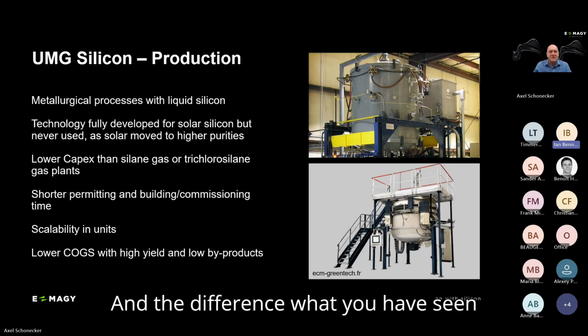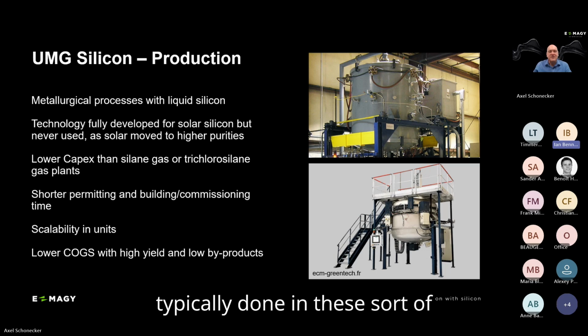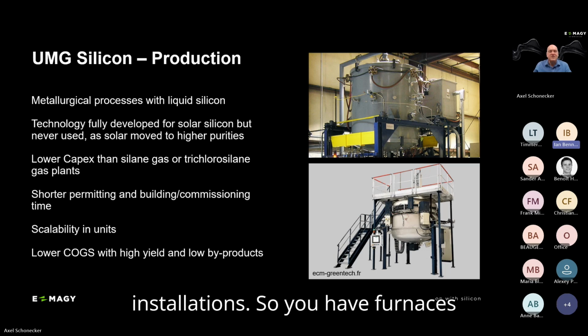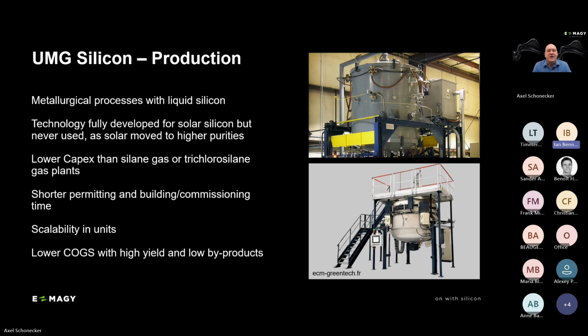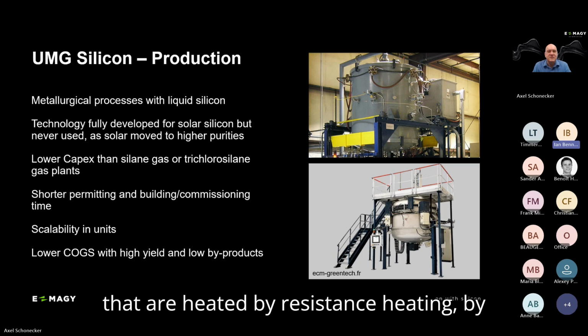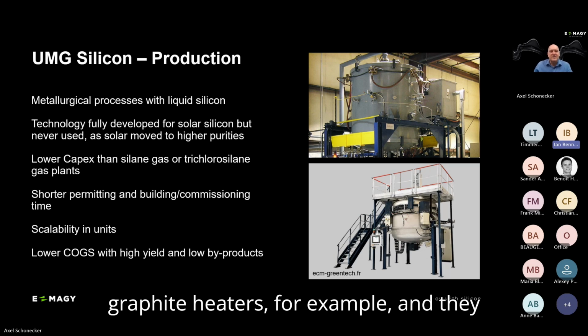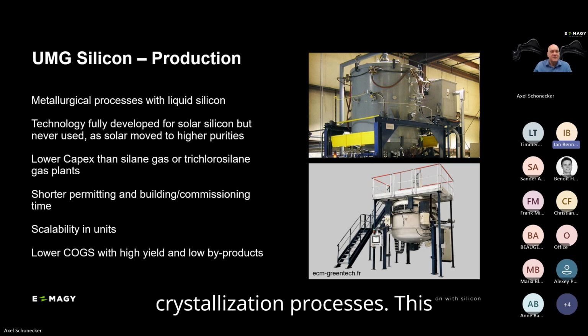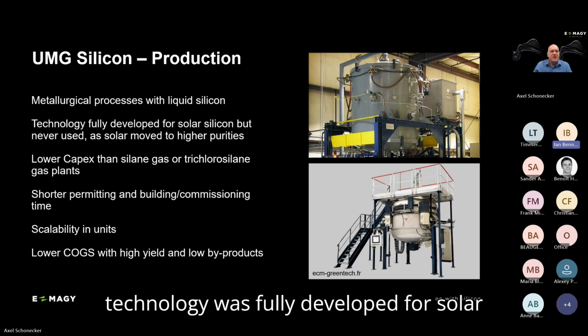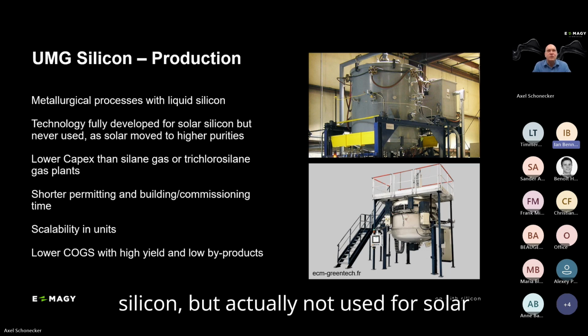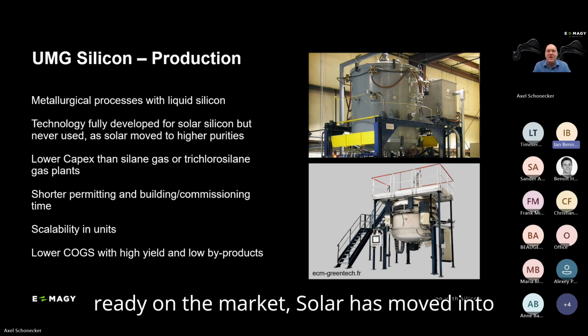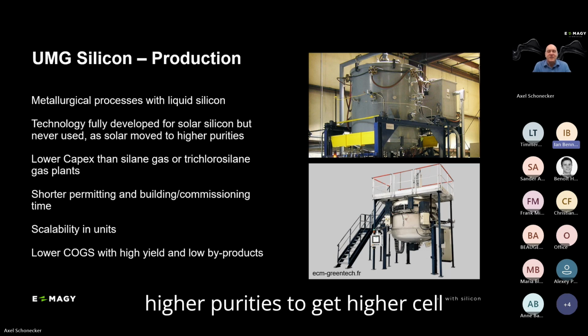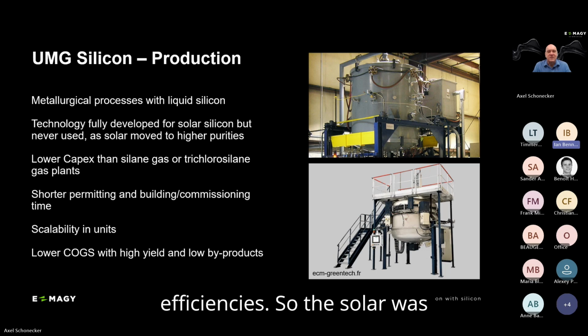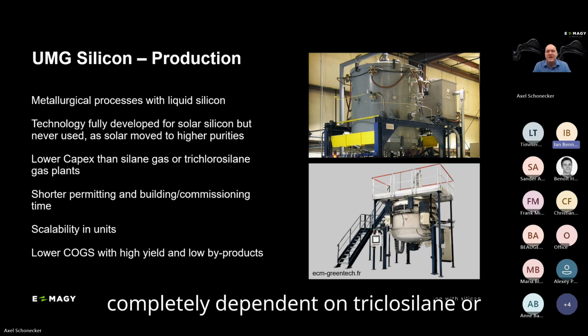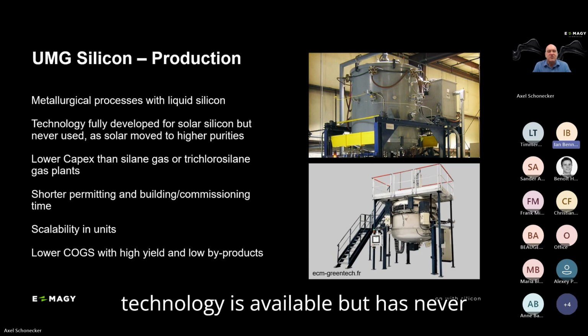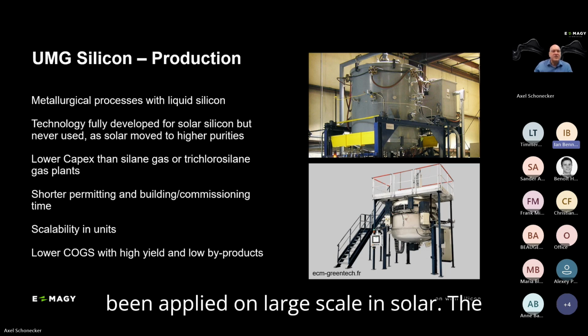And the difference, what you have seen with the chemical plants, is these are typically done in these sort of installations. So you have furnaces under argon or under vacuum that are heated by resistance heating, by graphite heaters, for example, and they deal with liquid silicon and crystallization processes. This technology was fully developed for solar silicon, but actually not used for solar silicon, because when the technology was ready on the market, solar has moved into higher purities to get higher cell efficiencies. So the solar was completely dependent on trichlorosilane or silane production. And actually this technology is available, but has never been applied on large scale in solar.